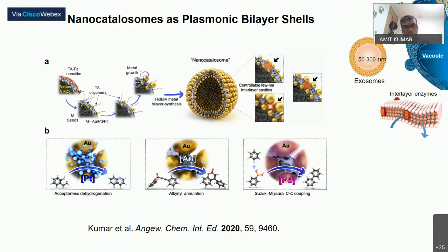So we came up with a new idea. Let's this time modify the catalytic site into hotspot regions. So we synthesized a bilayer. We call them nanocatalosomes, which look very similar to the natural exosome structures. Bilayer structures are very common in biology. And we modified these bilayer structures with different catalytic nanocrystals right in the hotspot regions for catalytic applications.